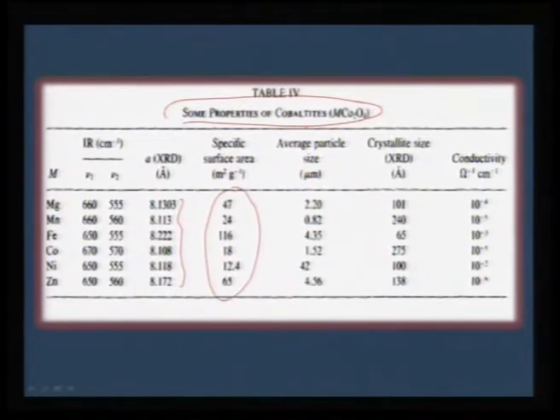And look at the specific surface area measured using the BET method. You can see here iron tops it all, which means iron cobaltite is the most reactive or the most voluminous in size, and as a result you can look at the average particle size and the crystallite size to be quite distinct from the other oxides. The crystallite size that you see from XRD is a true measure of the particle size, close to whatever you learn from TEM. So, it is roughly of the order of 6.5 nanometer, and because this is so small, the surface area is very large. Okay. And we can make several comparisons of that.